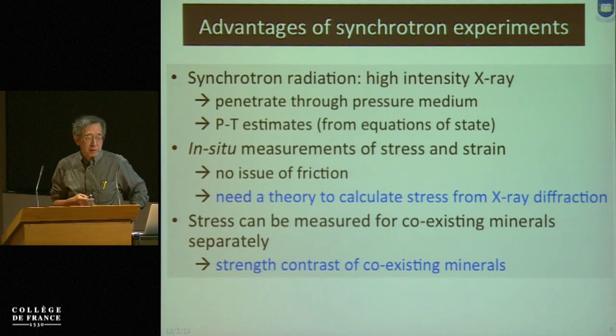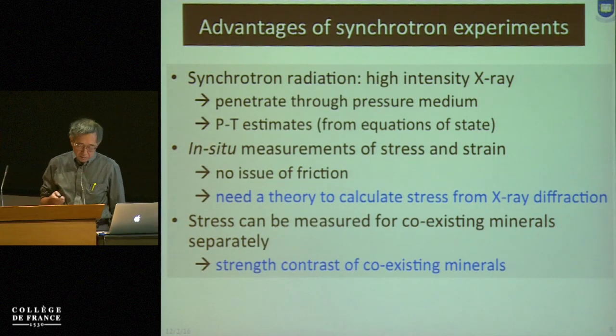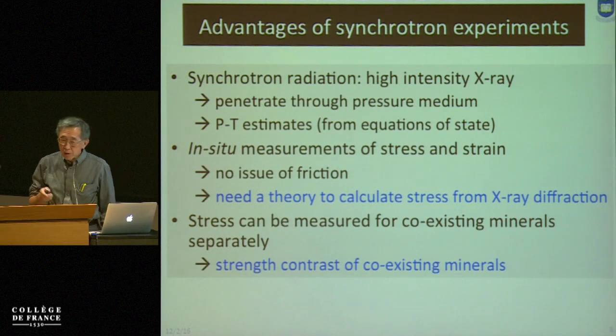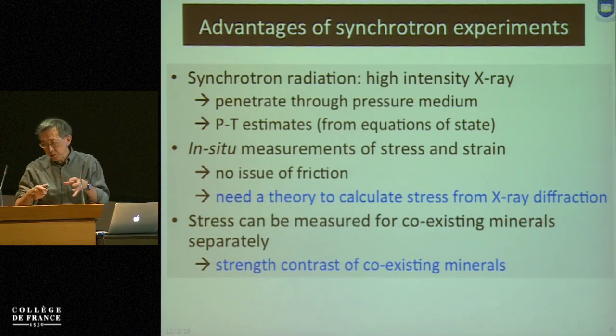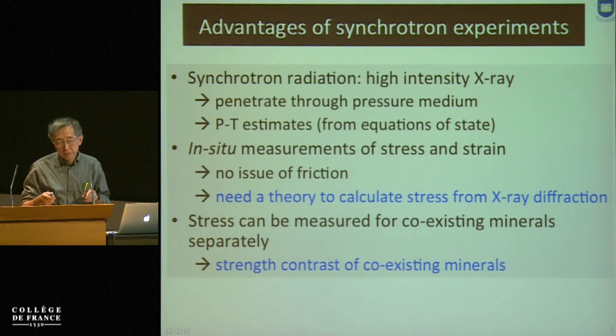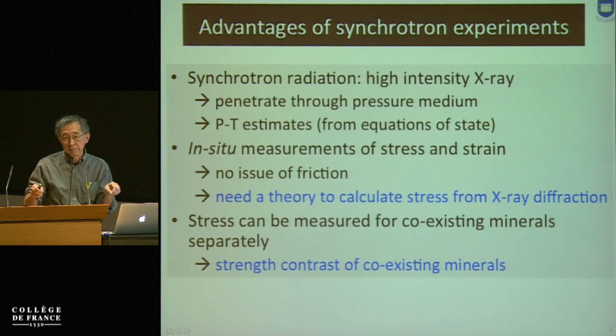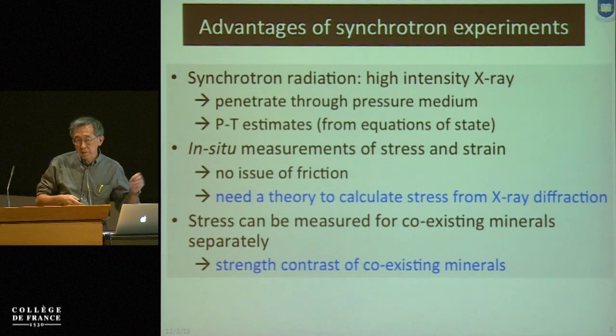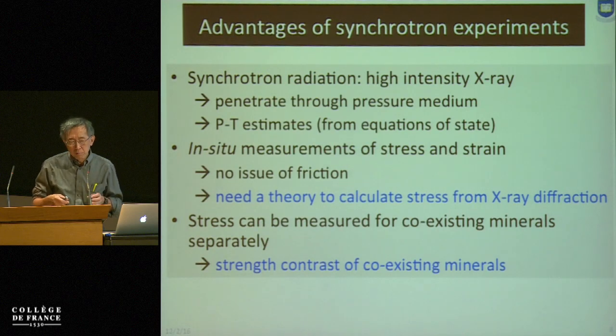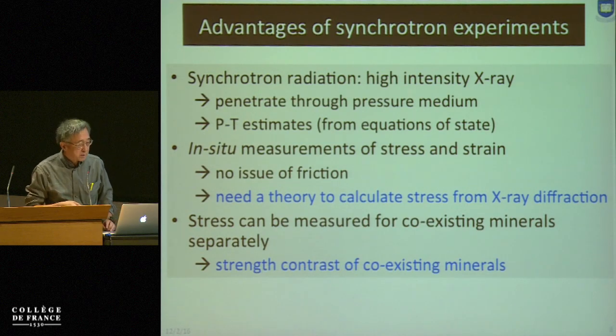Another big advantage is that by using X-ray, if you have two different materials inside your specimen, you can determine the rheology of the two materials separately. This you can't do with the conventional apparatus. All you measure is the macroscopic average stress. But with X-ray, if you have a mineral A and B, like bridgmanite and MgFeO, we are able to determine the strength of the two minerals so that you can really precisely constrain the rheological contrast. So that is a very unique advantage of a synchrotron facility.